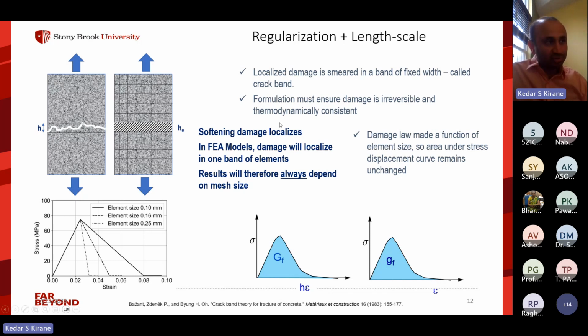But if the element size has to change, then the damage post peak has to be adjusted accordingly so that the energy dissipation does not change. So this is the simplest way to incorporate the length scale to get rid of the mesh dependence problem. And this is called the crack band model. And of course, it works for local damage models. There are other approaches, of course. There are gradient damage models, non-local damage models, but they are maybe more complicated. And this is the simplest approach, which is what we adopted.